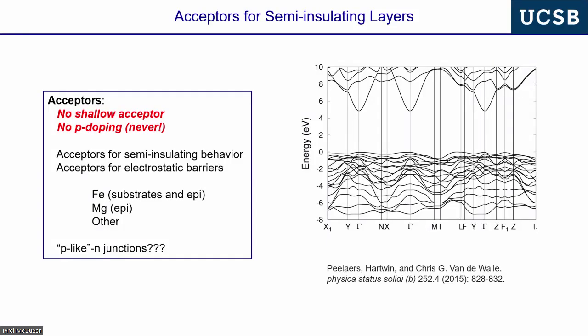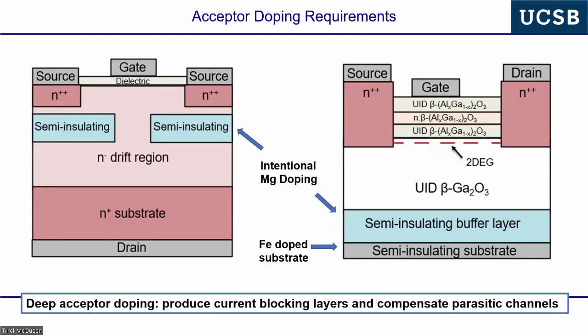NTT also developed magnesium-doped substrates, but I think they abandoned the magnesium in favor of the iron. Mostly, if you put transition metals from the middle part of the periodic table into compound semiconductors, you'll get semi-insulating behavior. So chrome, vanadium, molybdenum, almost any of these will lead to semi-insulating substrates. And if you have a good semi-insulating substrate, it's not clear which acceptor is better. But in GaN, where I work, there's still a lot of interest in developing improved semi-insulating substrates. In the last couple of years, manganese-doped GaN substrates are starting to look extremely promising, much better than the iron-doped semi-insulating substrates.